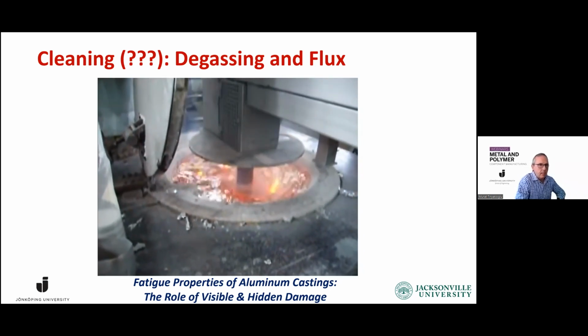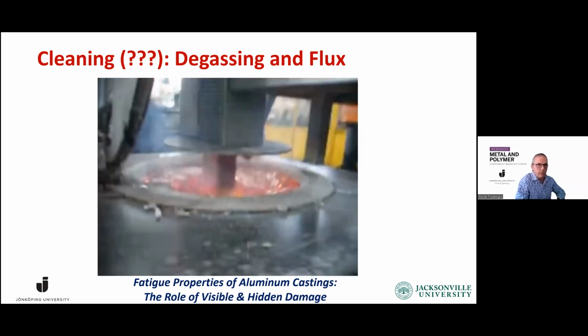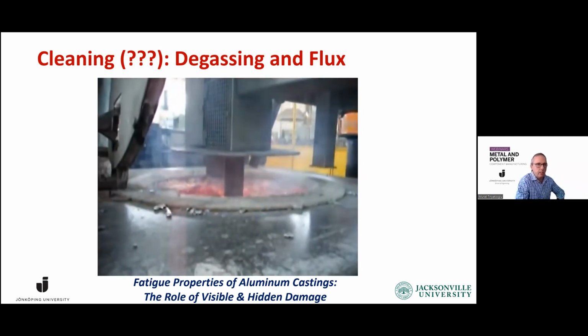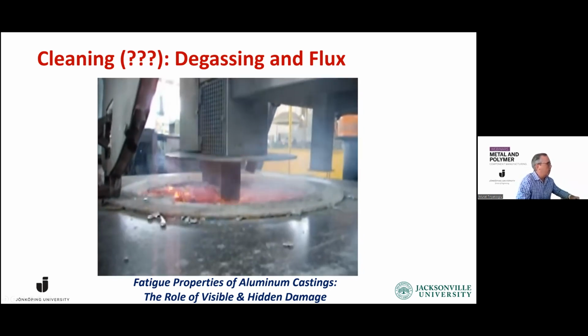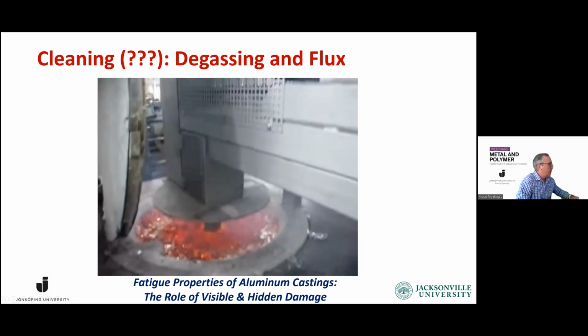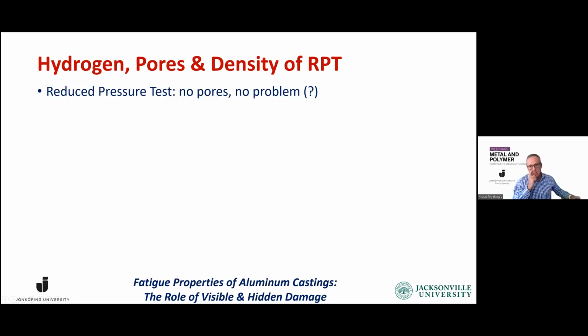And I think this is somewhat recent because degassing used to be much more quiescent, but recently this has become more and more common. So what we do with this approach is, perhaps some of you are familiar with the reduced pressure test, where we take a sample of aluminum and let it solidify under a reduced pressure. Then we chop it up and look inside, or weigh it and find the density. If we see no pores, we say, this is good, no problem, this is fantastic.